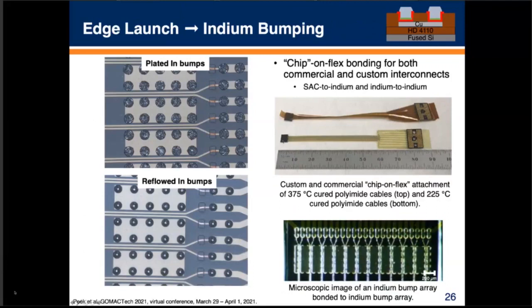Here it's attached to a small chip, and the image of that would look like this, looking through the top of the tape. You can see the bumps nice and smashed and lined up nicely. On the other end, we've got it connected to a commercially available connector. On one side, that's an indium bump. On the other side, these connectors come with SAC balls on them, so we've connected those directly to that. It's not a super concern in terms of the metallurgy there, because we're going to low temperatures.